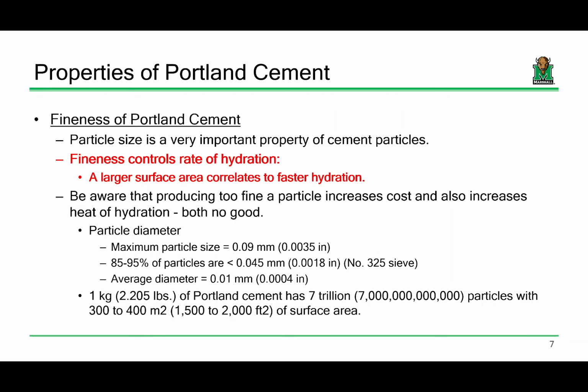Now the particle diameters for cement are really tiny. For example, most of the particles, if we were to do the math, would pass the number 325 sieve. They're pretty tiny particles. Just to put this in perspective, if you had a kilogram of Portland cement, so just a little bit, that's like 7 trillion particles. That's a lot. So this is what I was getting at when I said there's a lot of effort in the production of cement just getting it to the right particle size.